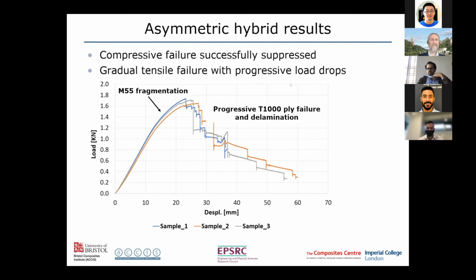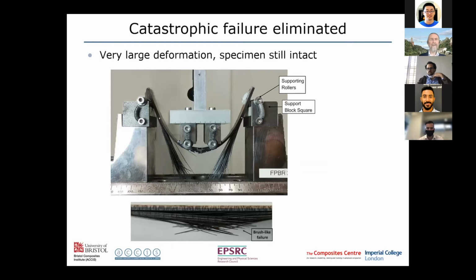And then we can go a bit further and the next ply fails and that delaminates. And then progressively we can continue loading, and what happens is it progressively fails through the thickness on the tension side, but still remains intact. And even at the end of the test, the specimen is still in one piece. So we get very large deformation. The specimen is still intact. At the final point, it just slips between the rollers and we can't apply any more displacement to it or any more load. And when we take it out of the test rig, you can see that it's now basically flat, but you've got these spears of the carbon fibers from these parts here, which have failed progressively through the thickness, but the rest of the specimen is still intact, and it can still carry an appreciable load despite the gross amount of damage which has been induced. So this is exactly the sort of behavior that we wanted.